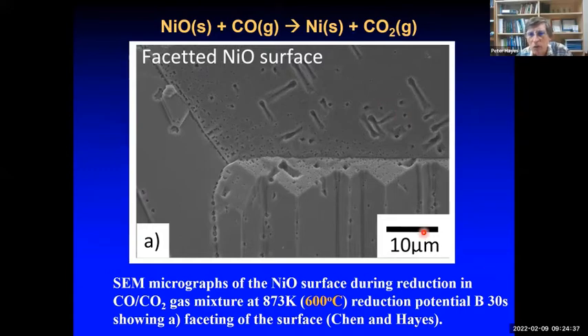You see we've got a 10 micron marker here. So we're looking at the surface of a nickel oxide, with the horizontal line here being the grain boundary, and we can see that there are, if you like, little holes appearing on the surface of the nickel oxide. These are called facets. What's happening is that the reactant gas is preferentially taking away the oxygen from the surface at certain sites. So it's not happening uniformly on the surface. There are certain planes where it's easier to take oxygen away from the nickel oxide than others, hence the faceting.